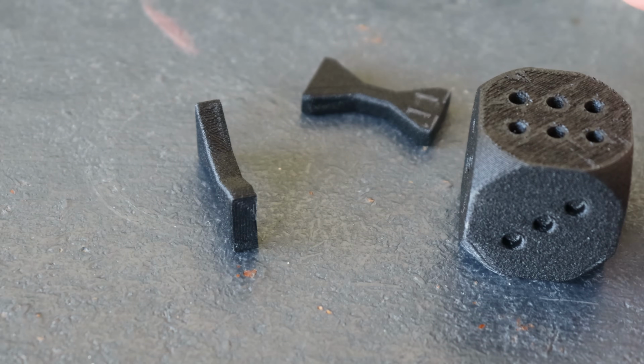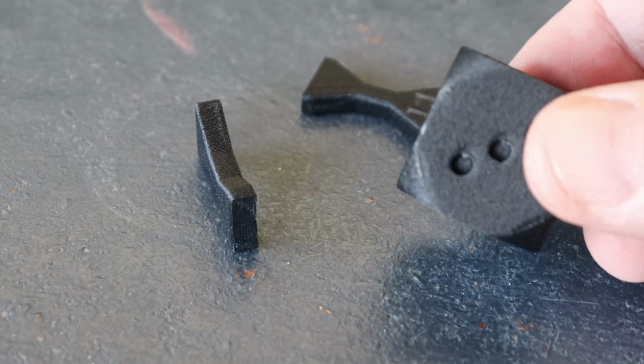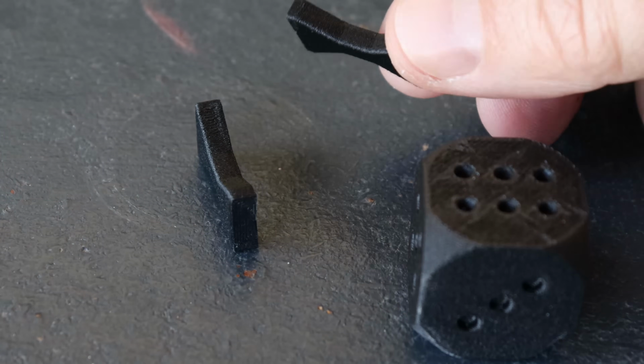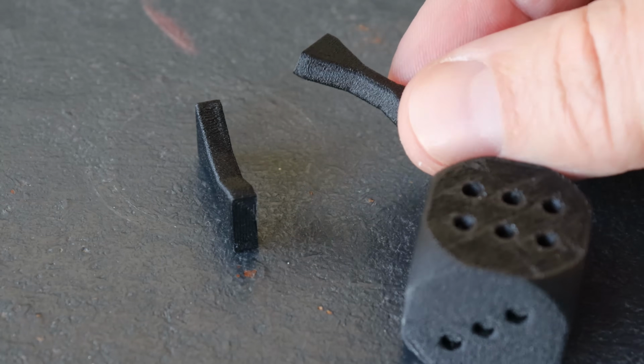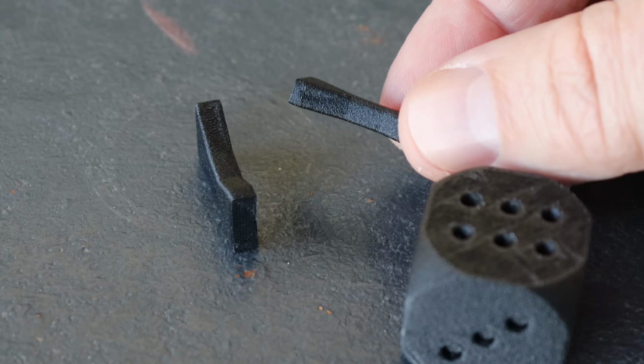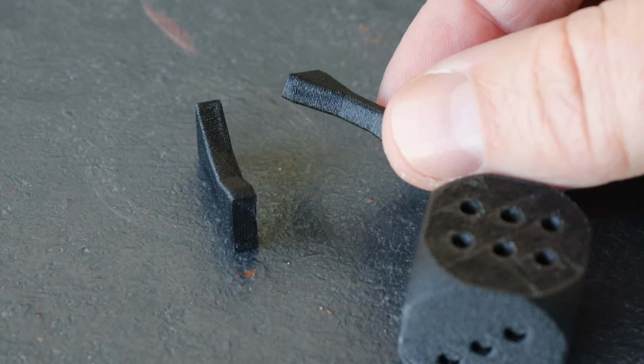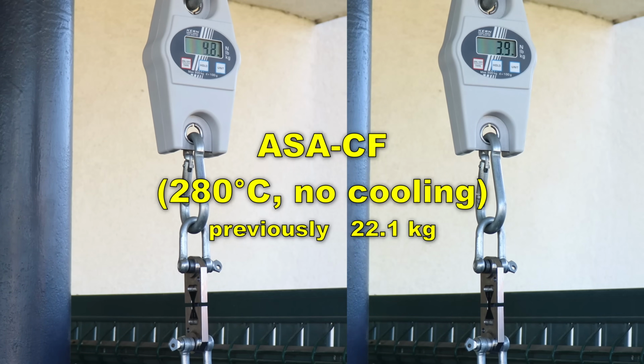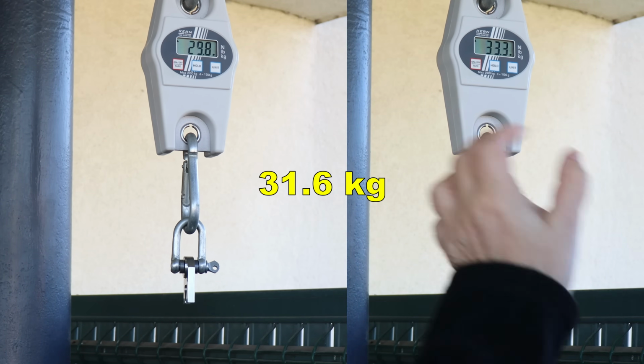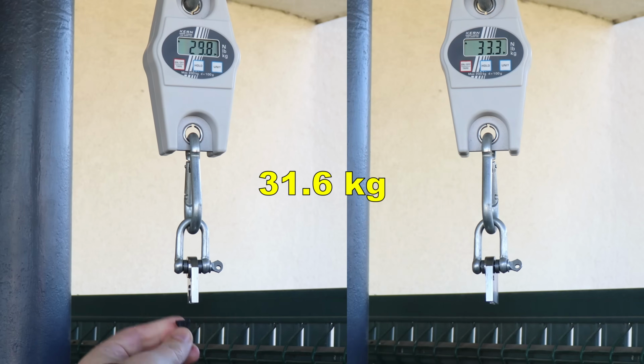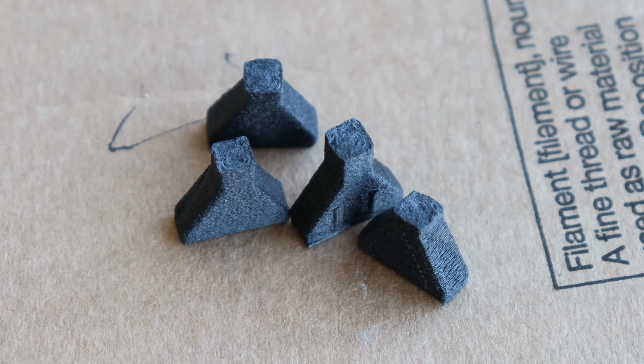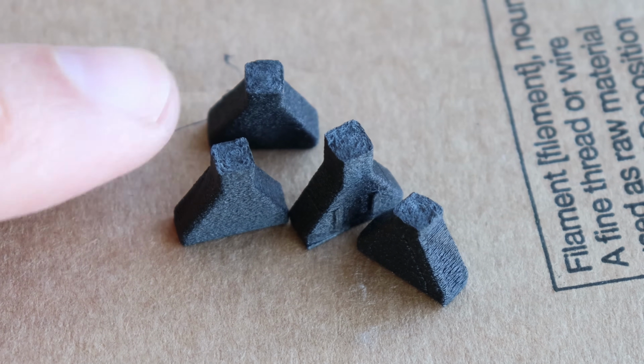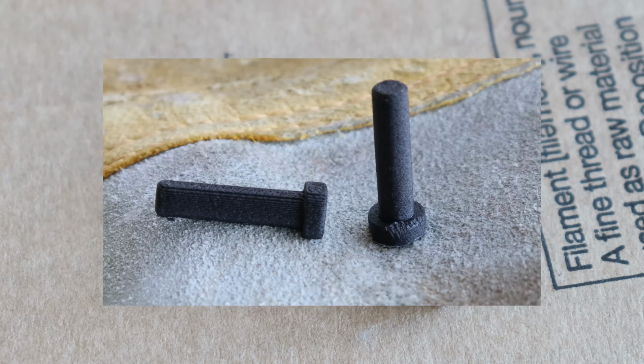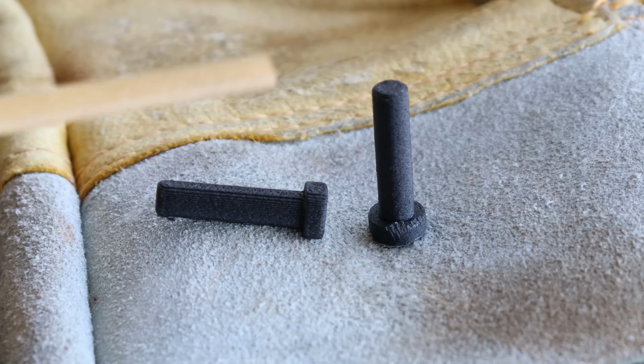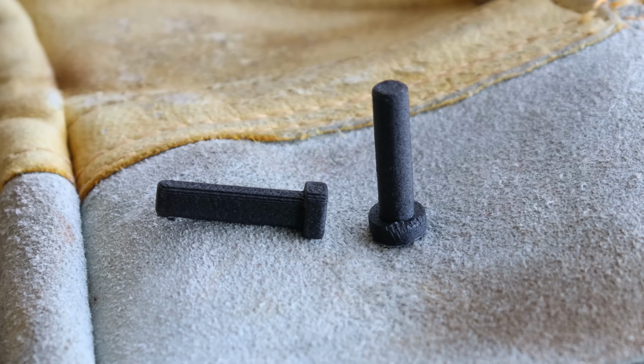Actually, this came out quite good, not perfect, and interesting matte surface we have here. But as you can see, it is very close to the failure, so it was printed correctly, but I couldn't go much higher with the temperatures. This was significant improvement. Maybe it deserves a separate video to see how much higher can I go with the print temperatures. Two-sided shear stress with the horizontally and vertically printed test objects with the same dimensions.